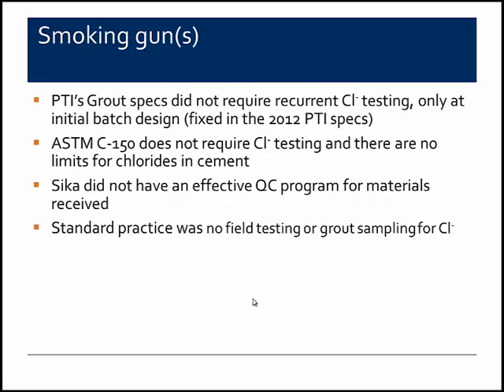During the course of this investigation, there were some issues that were brought forward to the industry related to quality control, grout production, and specifications. One of those is that, as I mentioned earlier, the PTI grout specs in place at this time, the 2003 version, did not require recurrent chloride testing. It was only required during the initial batch design. So the 2012 specs now requires a chloride test on every production lot of grout so that you will get recurrent chloride testing. In addition, the traditional cement used for grout, which is an ASTM C150 cement, that ASTM C150 specification does not require chloride testing of the cement, and in fact there are no limits for chloride in cement in that specification. And that has not yet been addressed to my knowledge.